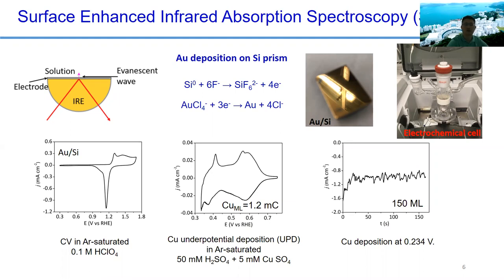We know that infrared has a big problem due to water absorption. A lot of signal will be absorbed by the aqueous electrolyte. So in order to minimize the effect of the water, a typical experiment in electrochemistry is using external reflection. Basically, if you have a reflective element, for example silicon or zinc selenide, the working electrode gets pressed on that element, forming a very thin liquid layer, typically 10 micrometers. Okay.